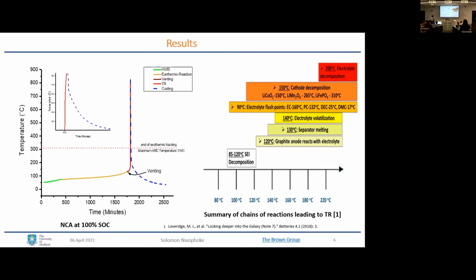There is a little drop in temperature. Gas generated from within the battery tends to absorb some heat and results in a little moment of cooling, and then it proceeds to thermal runaway, which is a speedy reaction that releases a lot of heat and sometimes causes fire. So this is a zoom in of the thermal runaway region. The temperature of the battery increased sharply to a maximum of about 824 degrees Celsius and then cools down. That's a sample of the plot.